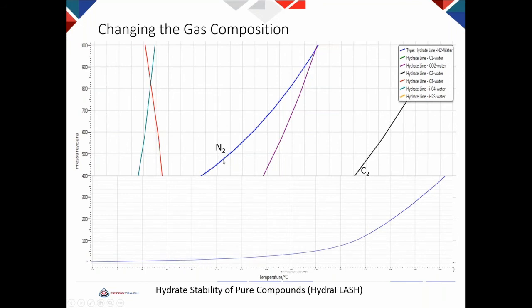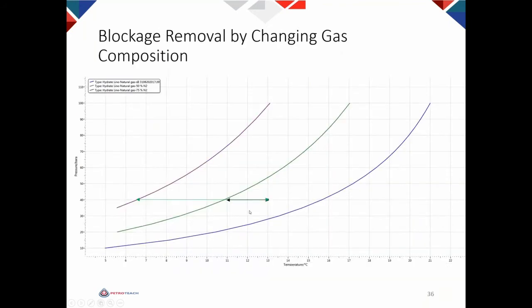You see that if I add nitrogen, it will shift the hydrate phase boundary. And here I've taken the gas hydrate phase boundary of the gas I mentioned to you, 85% methane, and assume this is the operating condition. So it is inside the hydrate phase boundary. This was in fact a real case. The pipeline was blocked, and there were two pigs, and they couldn't inject any inhibitor, but they could inject nitrogen. So injecting nitrogen, when it reaches the blockage, changes the composition of the gas there.